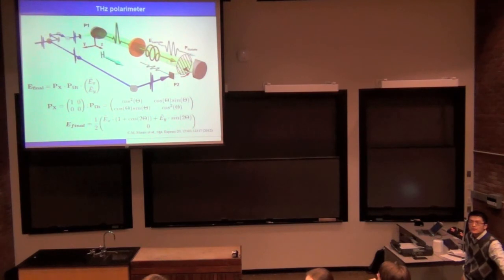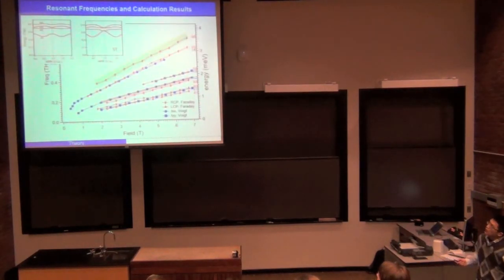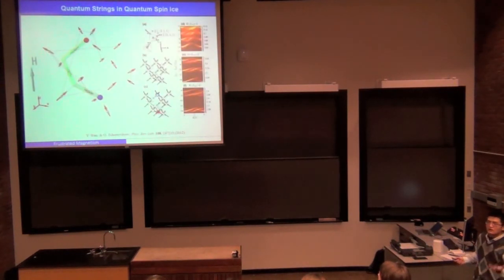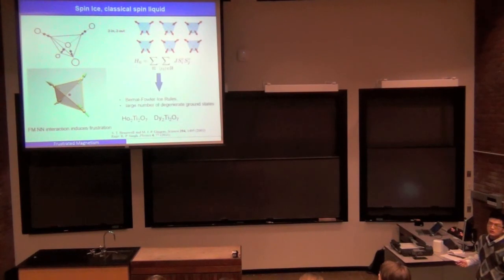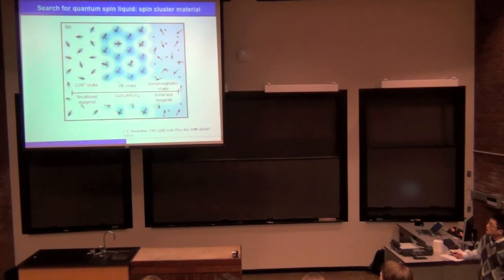Thank you. Just a question on this 2D spin cluster material. What was the RVB ground state that you were proposing? Because it looked like it's effectively a triangular lattice, but they're not resonating on the triangular lattice? Right. Because below 100 K, effectively 2/3 of the spin seems to disappear, so they believe those 2/3 of the spin condense into a resonant state. However, 1/3 of the spin is still in a paramagnetic state. So it's a coexistence with this resonating valence bond state. This spin, for example, would be in a paramagnetic state, but the neighboring spins would be in a valence bond state. But this structure is not static, it's believed to be dynamic. As a result, they think it's still a quantum spin liquid state.